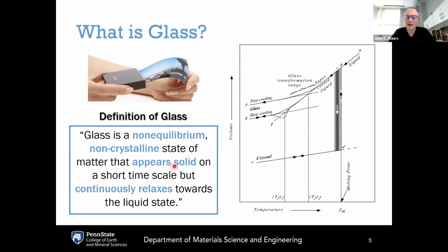It appears solid on short time scales because if you say knock on a piece of glass, you're probing that glass on a time scale that is too fast for the glass to be able to have configurational rearrangement. So it appears solid if you probe it on a short time scale, but on a much longer time scale, it continuously relaxes toward the supercooled liquid state because it wants to try to find its metastable equilibrium. So this is the formal definition of glass, and you'll note that this definition doesn't say anything about the chemistry of a glass.